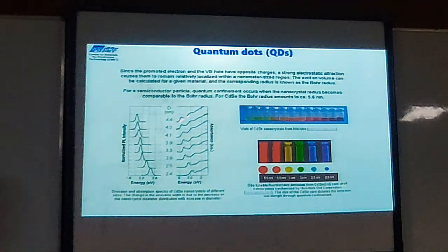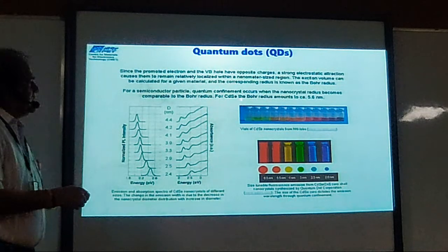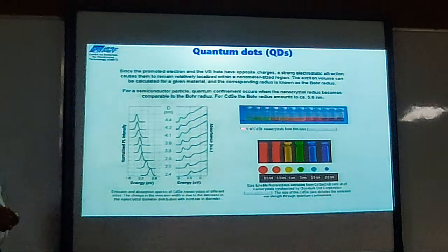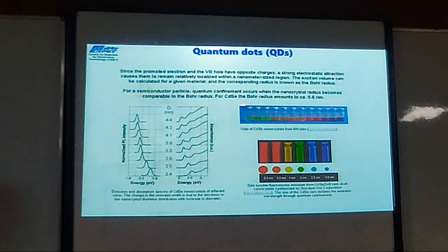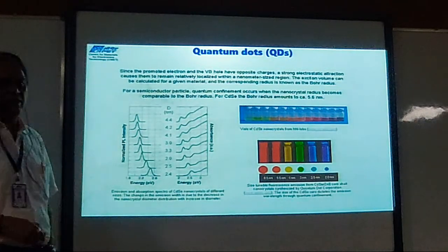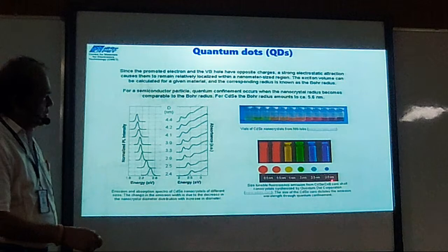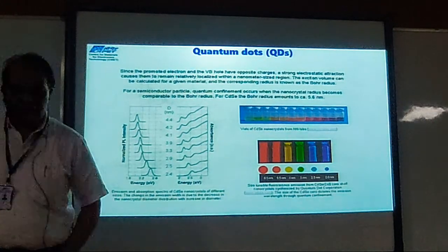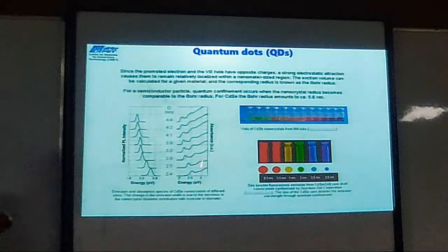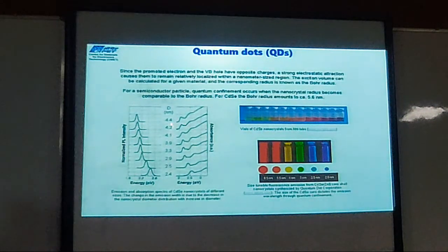Then quantum dots, which are very, very important. Like when you have CdSSe, cadmium sulfide selenide, they absorb well in the visible region. The Bohr radius of CdSSe is 5.6 nanometers. If you can synthesize CdSSe in the range of 5.6 nanometers, it's called quantum dot size. So we can have 2 nanometers to 6.5 nanometers, and we can have all colors. This is quantum dot stuff. They will be useful in LEDs, so whether we can have stable quantum dots, because we can have the size control and all these colors in one compound.